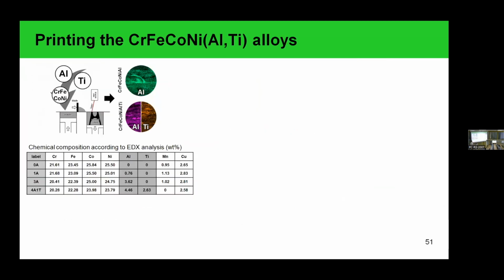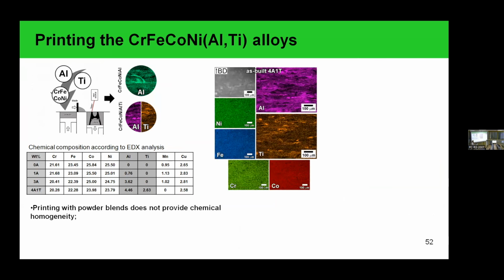And in the last stage, we analyzed the properties of our materials, which are alloyed with aluminum and titanium. And we compared, mostly focusing on the materials with the higher aluminum content, like 3.5 aluminum, and the aluminum with titanium, in comparison with the small aluminum content and the 4-component system. And as was in the case of the small aluminum addition, in case of the materials with aluminum and titanium, we observed the strong chemical inhomogeneity of our materials.